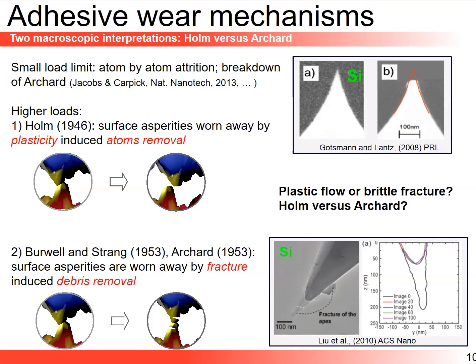And there, historically, going back 70 years ago, there were 2 competing theories. A theory from Holm saying that when you form an adhesive bridge between 2 asperities, here in the schematic, the strong adhesive forces, as you shear your system, are going to move past each other by plasticity-induced atom removal. Archard and others said, no, when you form an adhesive bridge, you're going to get cracks and you're going to form a debris. You see it here at the bottom, and you have even evidence from atomic force microscopy, with tips that are broken, and you see a tip that has been broken and is being attached to the side of the AFM.